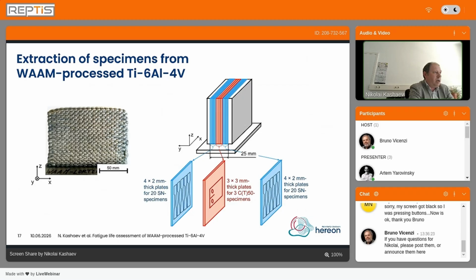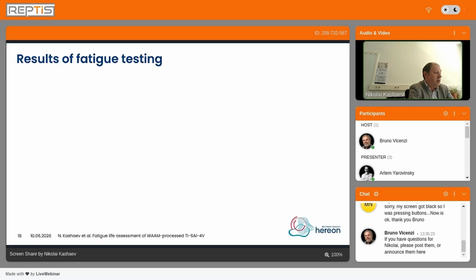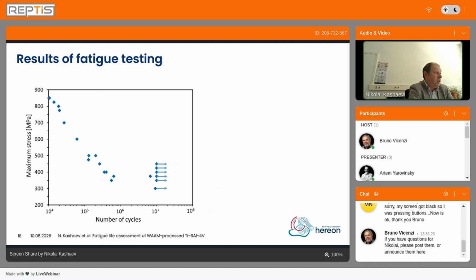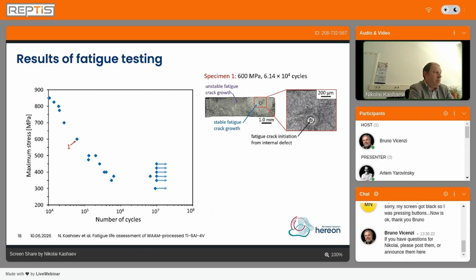And then we extracted from the manufactured block the specimens for investigating the fatigue behavior as S-N behavior, and we extracted also the CT specimens to investigate the fatigue behavior with regard to fatigue crack growth, to identify the parameters of the NASGRO equation to predict the fatigue behavior. And here are the results of predicting the fatigue behavior. In principle, here we have both situations. We have also fatigue cracks propagating from internal porosity.